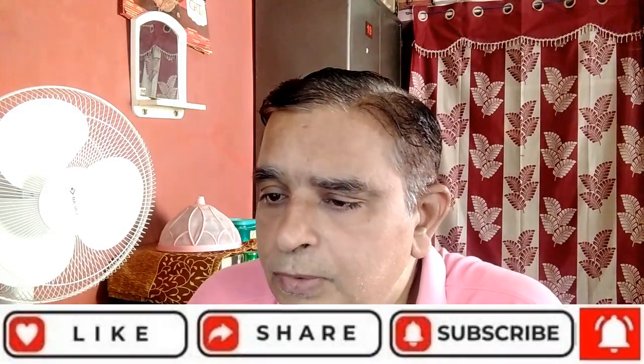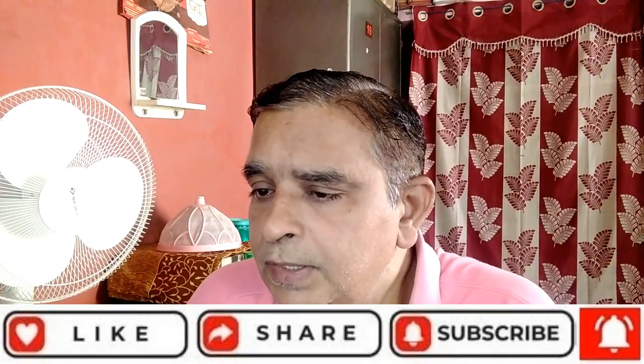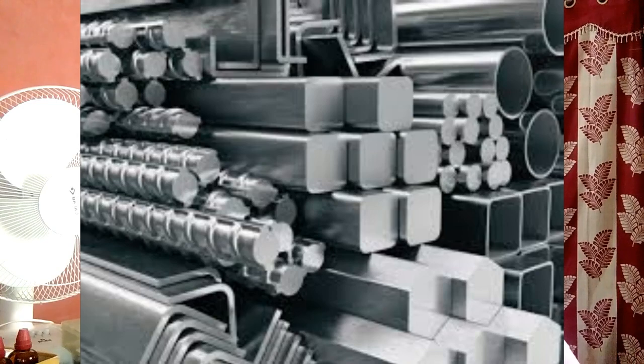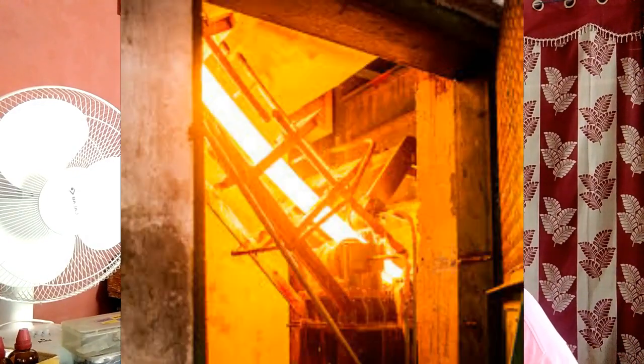Next point is the TMT bars are then subjected to heat treatment in three successive stages through an international process. First stage, quenching, starts with the hot rolled bar leaving the final stand and immediately being quenched by a special water spraying system. The process results in the formation of martensite in the outer surface of the bar while the core remains austenitic.